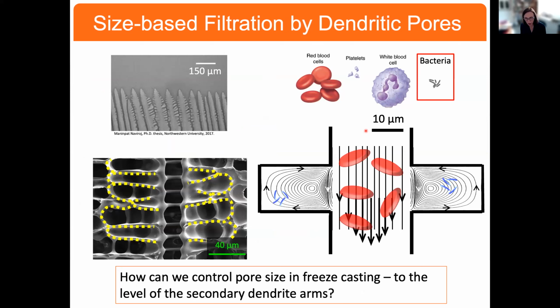Okay, so again, how do we control that? Here's the dendritic structure that we see on freezing. This is the resulting microstructure. And again, what we're suggesting is that the red and white blood cells would continue through the main channel here, with the bacteria particles being caught up in these side channels at very, very slow flow rates. Another important aspect of this is that the number of these side channels is significantly larger than the main channels.